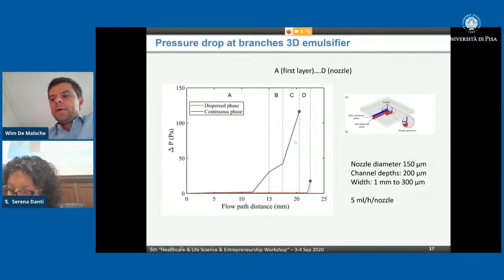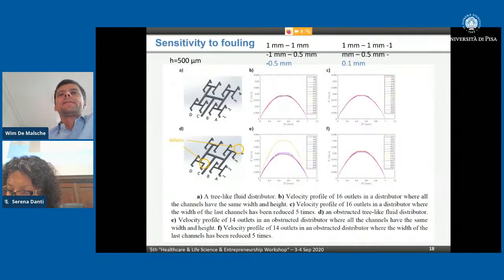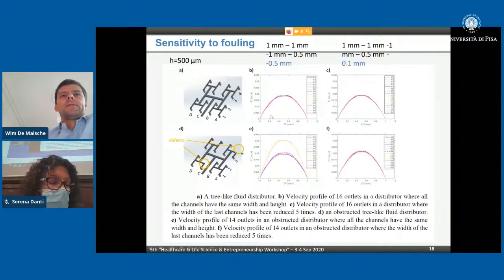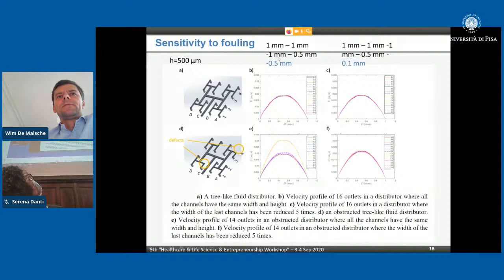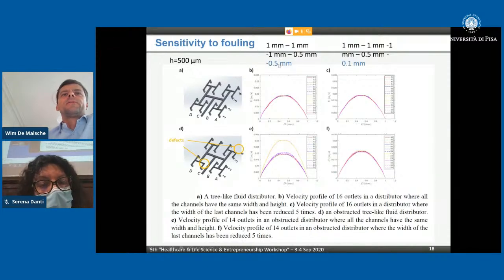And that is highly relevant as we are making particles out of our droplets. We are having solid materials, and sometimes we have uncontrolled precipitation, so this is something to take into account. Studying this, you can see here again the dimensions of the different layers going smaller and smaller. For the final channel, the depth is 500 micron, the first width is 1 millimeter, and the final width is 500 micron. If we include defects now, these are 16 nozzles that we have here.